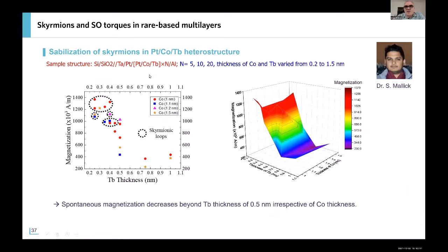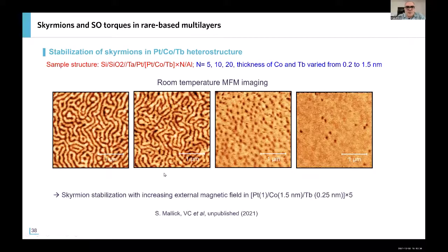the thicknesses, we can vary the number of repetitions, and we find that there is in fact a spontaneous magnetization when we have thicknesses of the terbium that are relatively small, below 0.5 nanometers. And interestingly, in this range of thicknesses, we were able to observe some skyrmions that can be stabilized in the multilayer. This is shown here by magnetic force microscopy imaging that is in this case extremely difficult to obtain because the signal is very weak and very sensitive to the interaction with the tip.